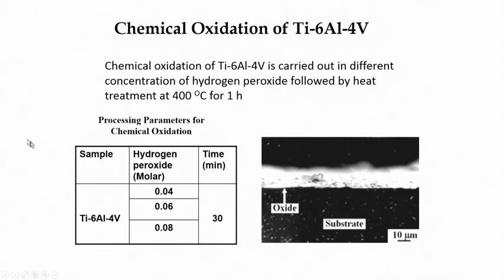Here the Ti64 substrate was initially cleaned very nicely, then polished to a level of 0.25 to 0.5 micron, and then subjected to hydrogen peroxide treatment and then heat treatment. After the hydrogen peroxide treatment, a jelly kind of substance was formed on the surface, and when it was heat treated, a very thin oxide layer was formed on the surface.